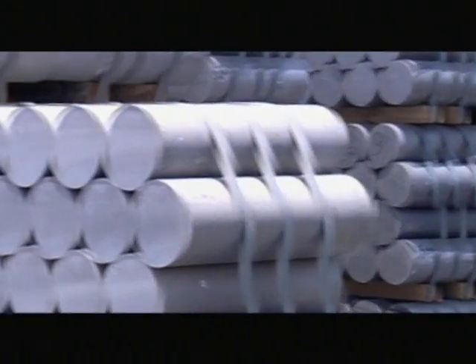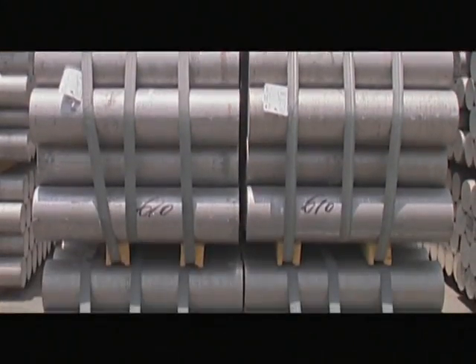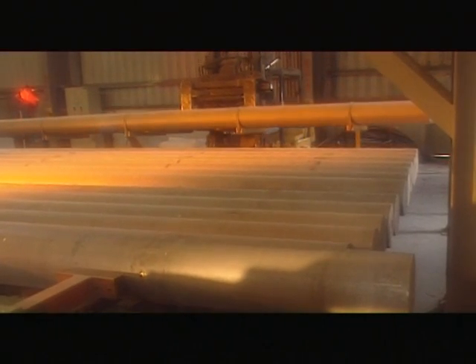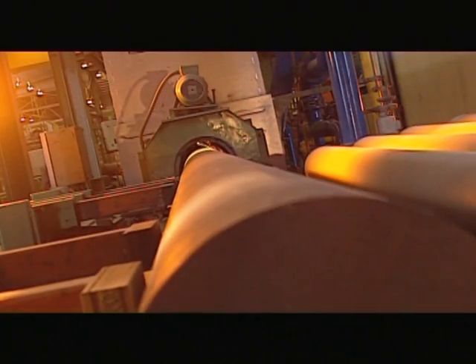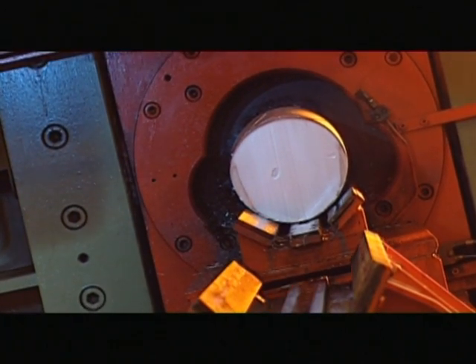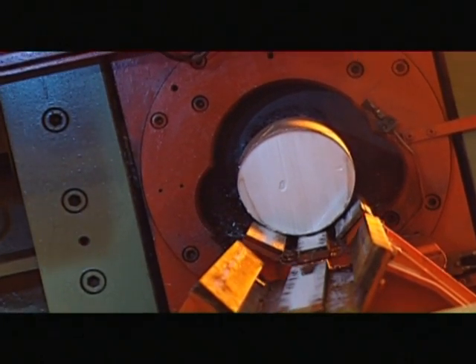The aluminium extrusion process begins with cylindrical aluminium alloyed billets. These billets are heated to over 450 degrees centigrade to increase malleability, so as to be shaped by one of the thousand precision-engineered dies on any of the large extrusion presses.